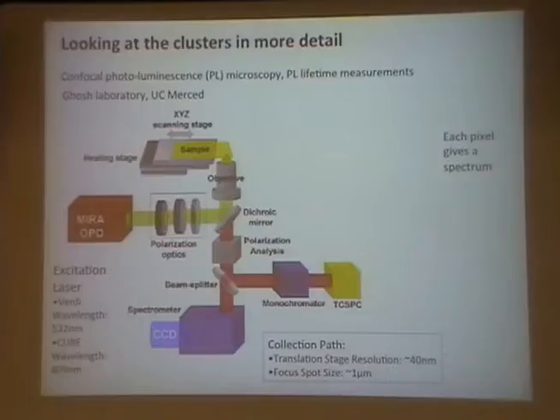This gives us information not just on the spatial arrangement of particles, but also on their emission properties. We can look at the emission wavelength, how it changes depending on if they're close to each other or far apart. I mentioned the FRET analysis: they transfer energy and that changes their emission properties. And we can also look at the fast lifetime behavior of the quantum dots. When they transfer energy between each other, that interaction has a short lifetime compared to when they're on their own, when they just absorb a photon and then re-emit nanoseconds later. So using this setup, we can get quite a bit more out of the imaging and spectroscopy rather than just a basic microscopy image.